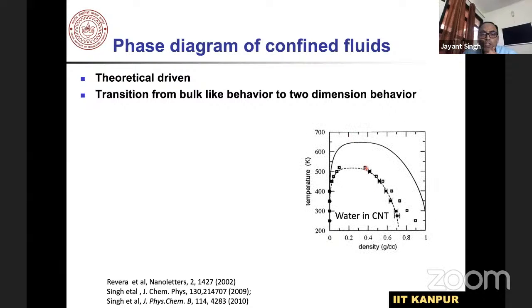So this is the first work which they did, and they said that, well, water perhaps behaves like that. So this solid line which you see is a normal water temperature-density phase diagram, whereas water in a CNT behaves in this form, okay? So our question was, does it only behave this way with water, or is it true for many other systems? And if it is, what would happen if we further squeeze it? Do we get a two-dimensional behavior? What would be the condition of the transition from the bulk-like, or three-dimensional, behavior to two-dimensional behavior? So these are the questions which we were pretty bothered by at that time.